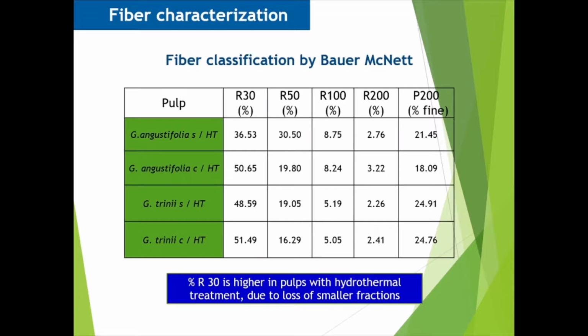This table shows a higher fraction of long fibers retained in 30 mesh, around 37 to 52% of fibers for all pulps. Pulps with hydrothermal pretreatment present higher retention on this mesh due to the loss of the minor fraction during washing in filtering.